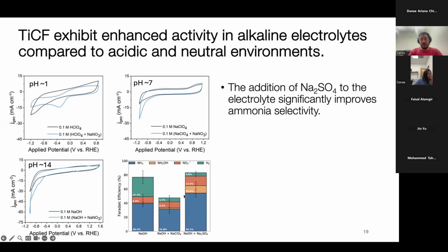And then we add different counter ions, we add perchlorates, we add sulfates, and we try to improve the base performance compared to just NaOH at pH 14. What we see is that sulfates generally lead to the best performance. The issue with perchlorates here is that it usually has worked well for us when we have bulk titanium or metal electrodes, but because we have a carbon electrode, I think the perchlorate ends up corroding that electrode, and some of the electrons actually go to that decomposition and corrosion of the carbon electrode, and that's why you see that the bar doesn't really add up to 100%. We think that some of those electrons are going to the degradation of our catalyst.